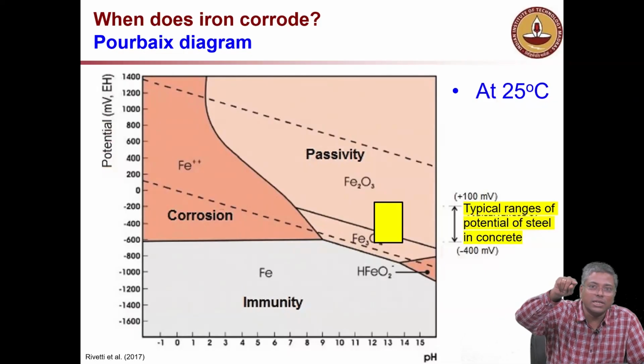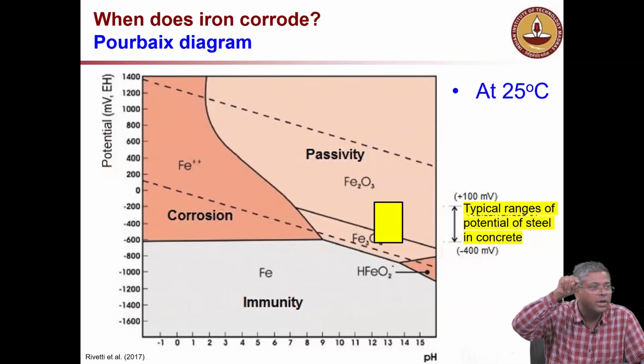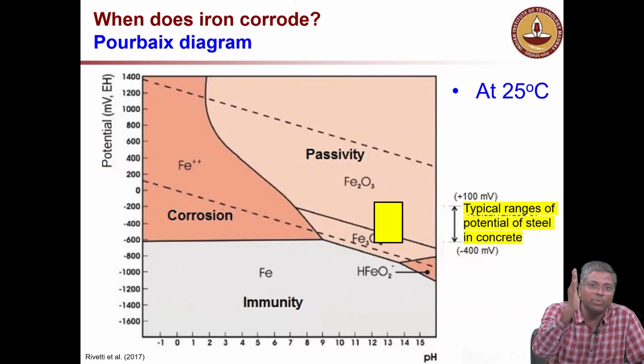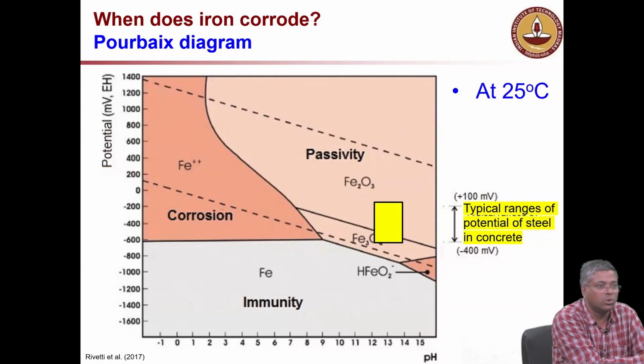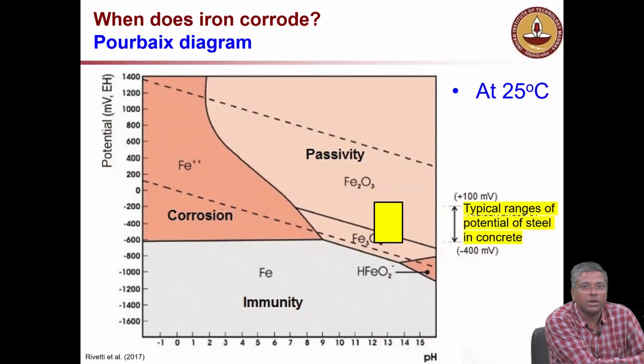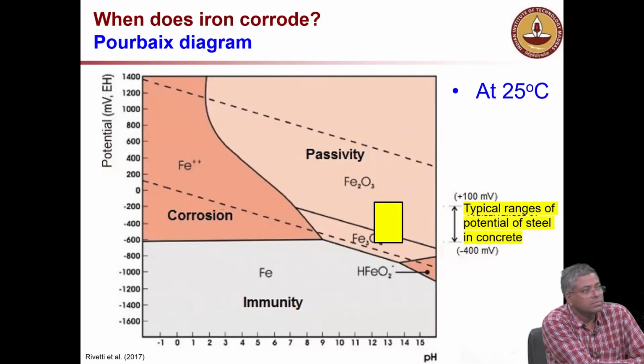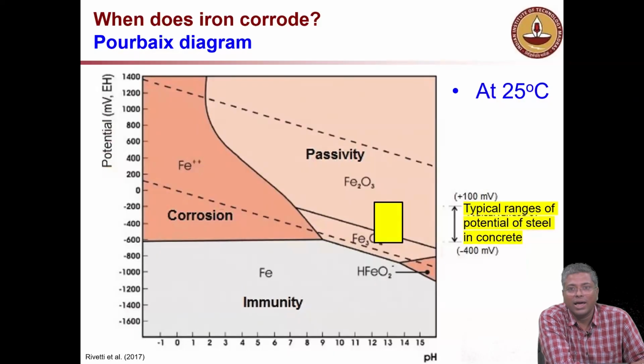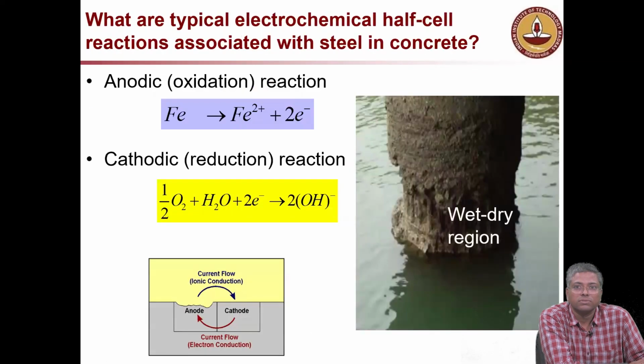Okay, so you see that corner over there, that V shape at the 9? From that point onwards to the left side, it is corrosion, the dark brown region, right? So pH 9 is very critical. You don't want a concrete with a pH of 9 or below because it will start corroding the steel.